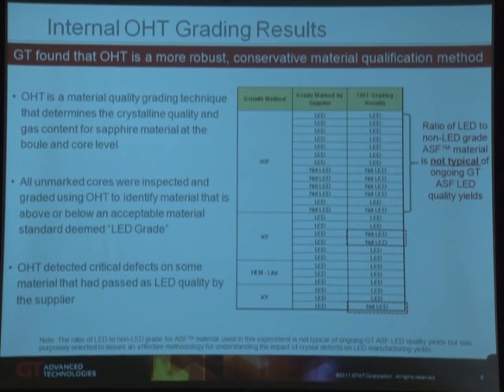In addition, we included from our ASF material that we knew was rejected and not LED grade material. This is not typical of our ASF process, but we wanted to make sure that we had a full statistical sample.